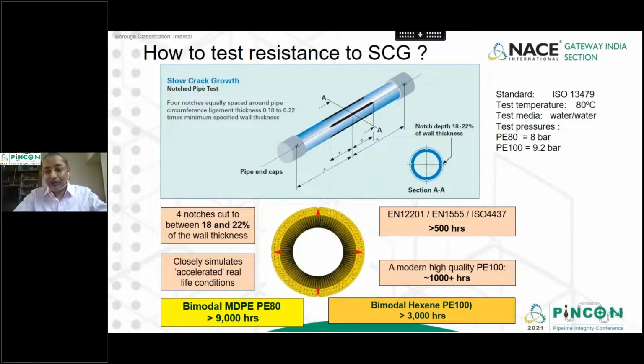A modern high quality PE100 gives about 1000 hours, whereas bimodal MDPE PE80 gives more than 9000 hours to failure in slow crack growth test, and bimodal hexene PE100 gives more than 3000 hours. So we have a lot of factor of safety to ensure 50 to 100 years service life.